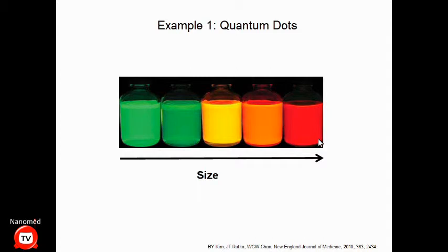Above 9 nanometers, the fluorescence is always red and doesn't change. But if you change the material to lead selenide, that number increases to 20 nanometers. The composition dictates where the tunability state of a material is — once it goes above that, color, fluorescence, and magnetic properties no longer change. However, 100 nanometers is a safe number indicating that most materials below 100 nanometers will have that tunable property. In some cases it's above 100, but for most materials it's 100 and below.